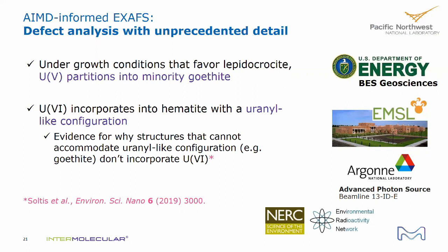Sure. So if you do the XAS, I'm assuming you're using FEFF to do XAS calculations with several different absorbing atoms in your clusters. But if you do that, FEFF and any other calculation engine will give a different E0 value depending on the local environment, the chemistry of your absorbing atom that you select. This could be pretty big for, say, uranium in an iron oxide or iron hydroxide versus a uranyl, where you have a very short bond, and that can give a pretty big impact on the E0 value that FEFF assigns for that calculated structure.